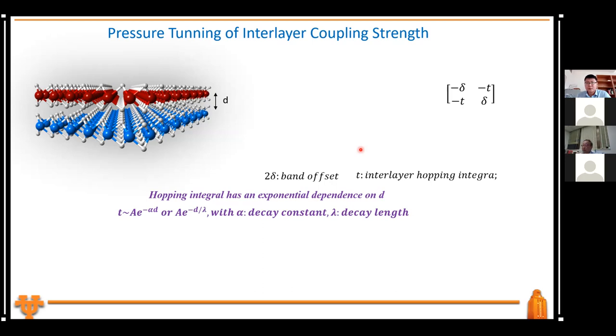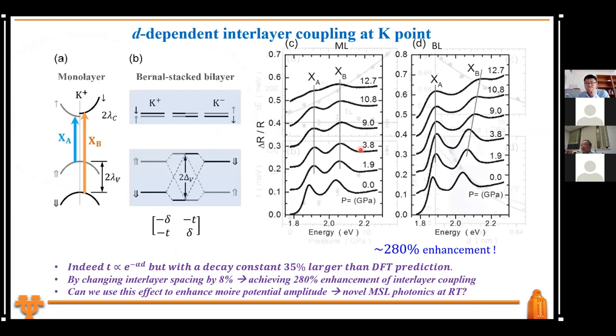When we are talking about trying to create all of these heterobilayers, the moiré potential is due to this geometric interference, right? That gives rise to this potential modulation. But the point of high interest for us is this KK coupling. The KK coupling is inherently very weak because of the orbital orientation. So in this work we have used hydrostatic pressure, putting them in a diamond cell, so we can change the interlayer spacing. By doing so, we can change the KK coupling by almost a factor of three. So I will end it right here.